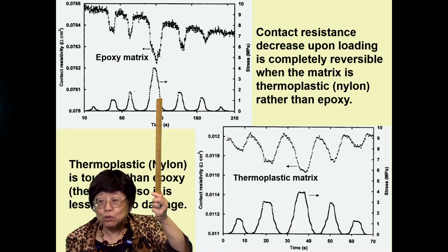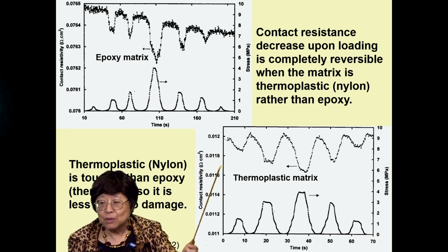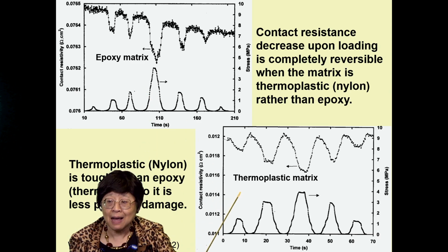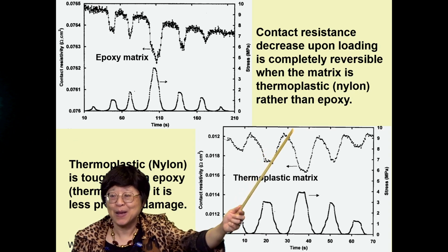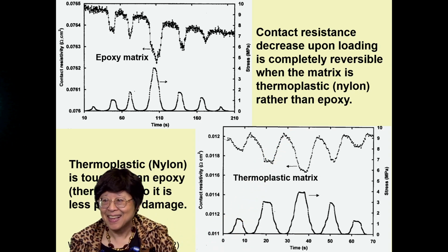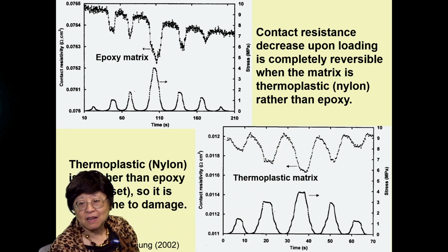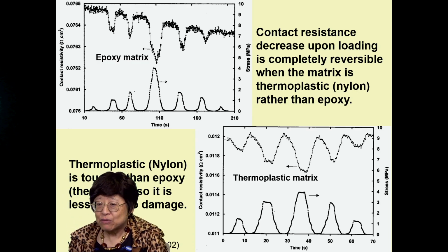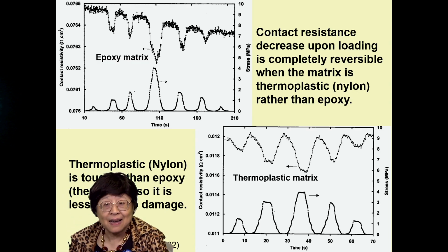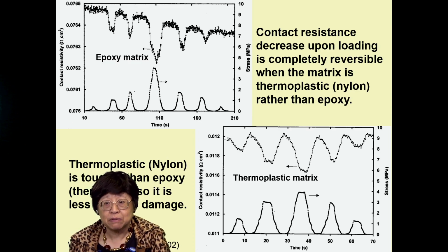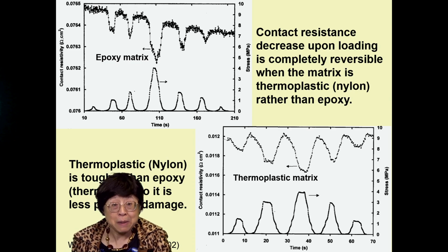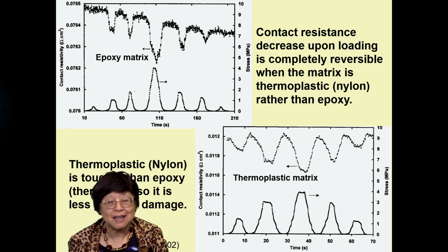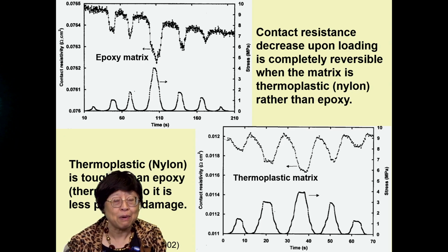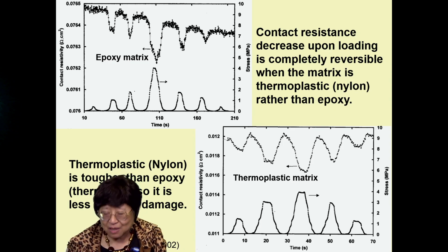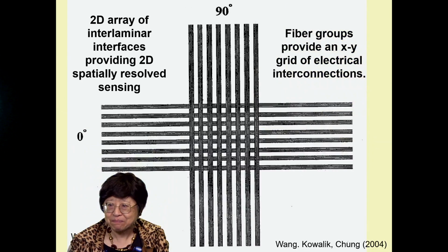However, if you don't use the epoxy matrix, but use a thermoplastic, such as a nylon matrix, it goes all the way back upon unloading. Okay? And that is because the thermoplastic or nylon matrix is tougher than the epoxy matrix, so it's less prone to damage. So it'd be better off if one uses the thermoplastic matrix in place of the epoxy matrix. But epoxy is still the matrix that's used for the aircraft structures.